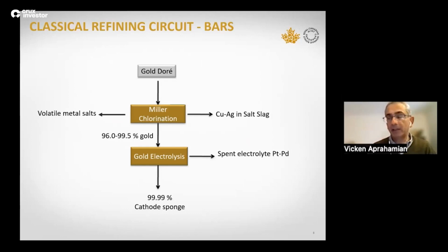This leaves behind molten metal after this first stage, which may have a purity of up to 99.5%. It is cast into anodes, and then it goes to a final stage of purification, which is gold electrorefining and the recovery of 99.99% cathode sponge. Platinum and palladium build up in the electrolyte system of electrorefining over time. So the solution is purified to recover these metals.